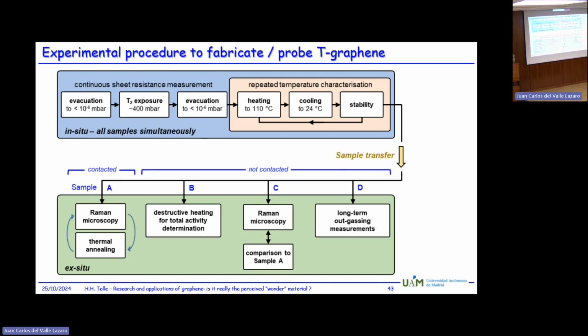And once you have done that, you can do loads of experiments, and the important one is here, the Raman microscopy, and then some comparison to check that everything is the same between the contacted sample and the non-contacted sample, because again, with the contact, you actually produce mechanical stress on the system. And you also want to be able to actually test whether it can serve as a tritium sample, like in the hydrogen fuel cycle that lives for a long time. So we are now, after 1 year, re-evaluating one of the samples to determine whether it still contains tritium or not.